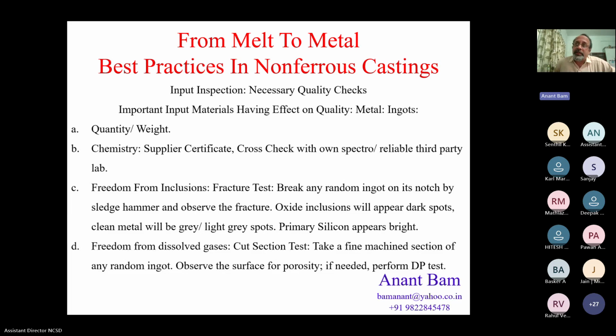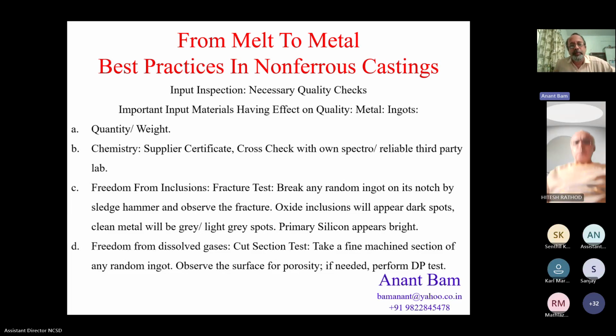Once it is verified that the supplier certificate and your own spectrometer certificate are matching, every spectrometer reading may not match perfectly, but they do match to the tune of about 90-95%. So if they match about 95% from the chemistry angle, the material is accepted. Third test or a third parameter to test is freedom from inclusions. Again, it's a commercial matter as well as technical matter. Aluminum is very prone to oxidation, and aluminum oxide or the dross is a killer element which kills your profits.